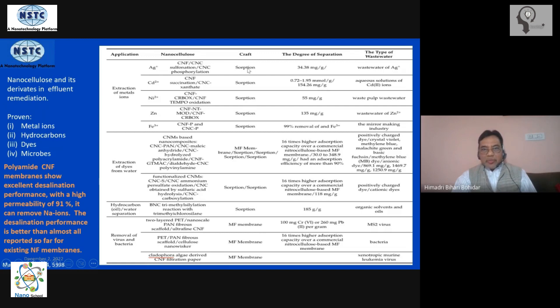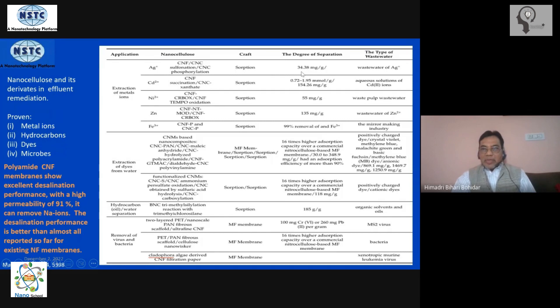The mechanisms for heavy metal removal are primarily adsorption — nano adsorption — and the degree of separation is something like 35 milligrams per gram of nano cellulose. In fact, it is 55 milligrams per gram for nickel and 135 milligrams per gram for zinc.